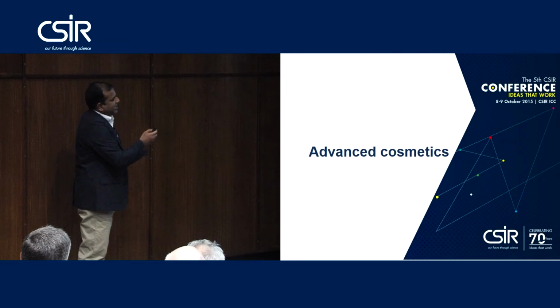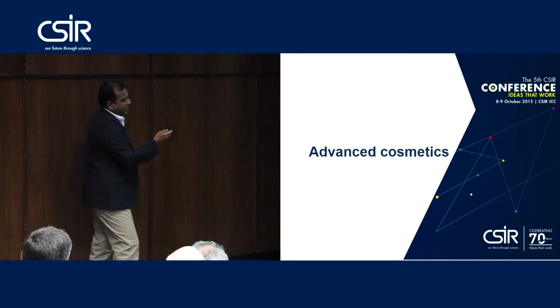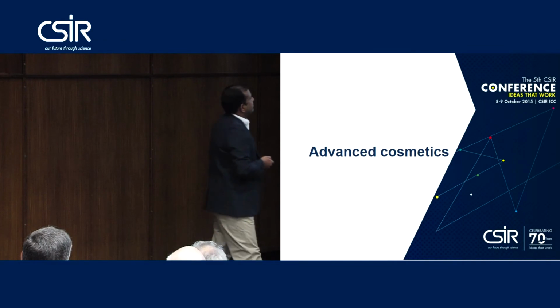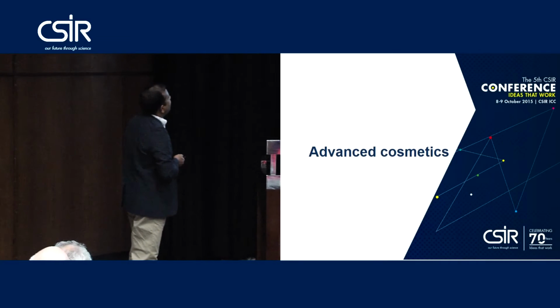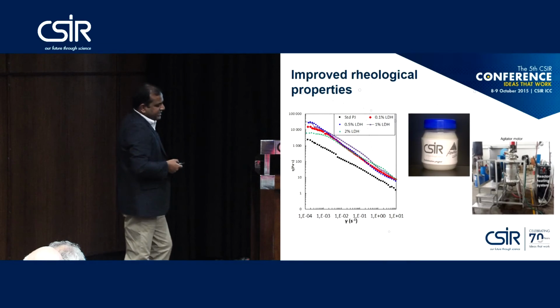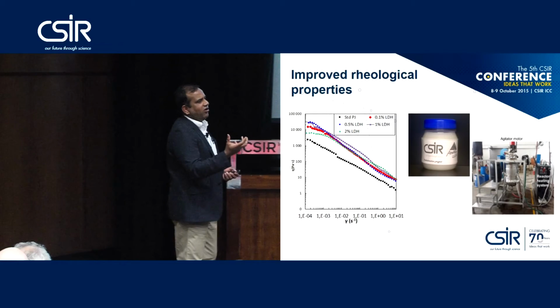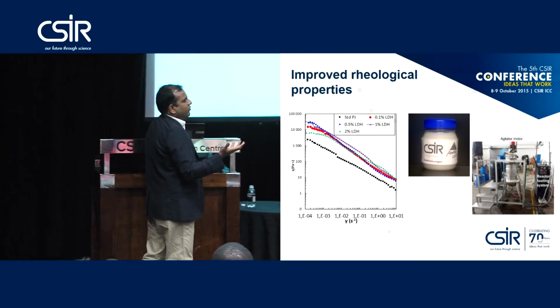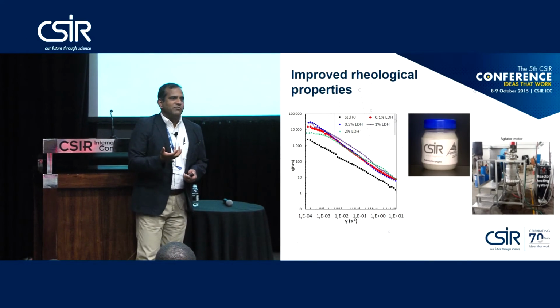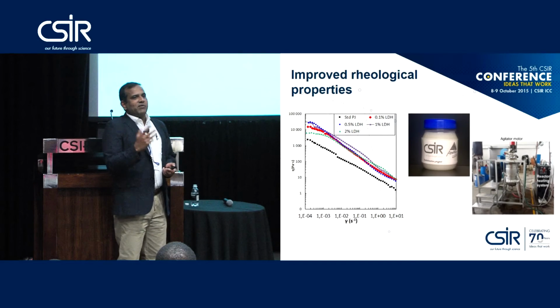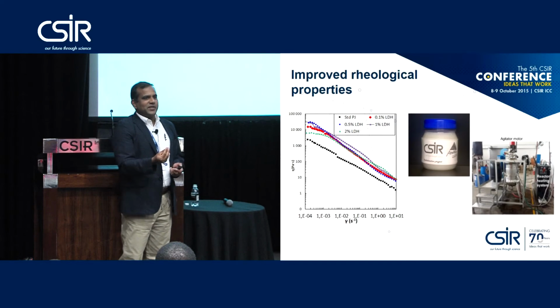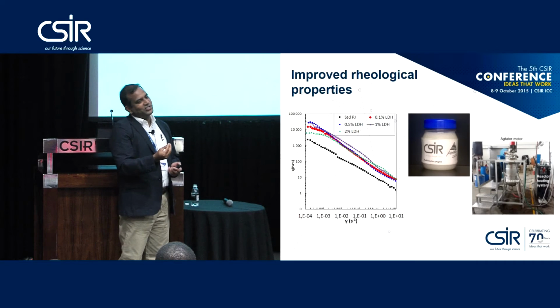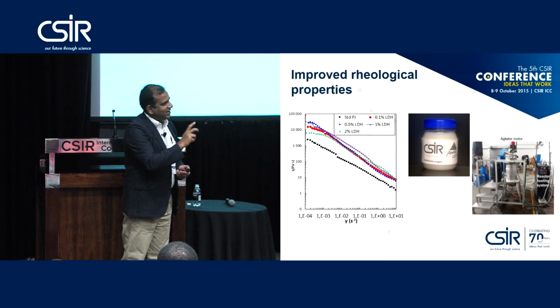Finally, we are doing some work that will soon be in the market because we are in the last stage. We have already signed the first step of the agreement, and the second, the commercial agreement, is going on, a technology transfer with AMCA. One of the biggest challenges is with petroleum jelly, which I think all of you use during winter. If you keep petroleum jelly for longer than 1 or 2 months, you will see discoloration, a yellowish type of color.